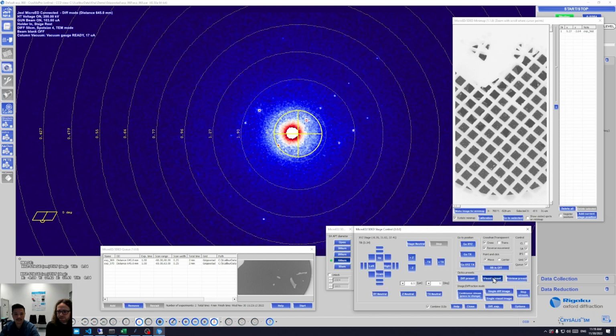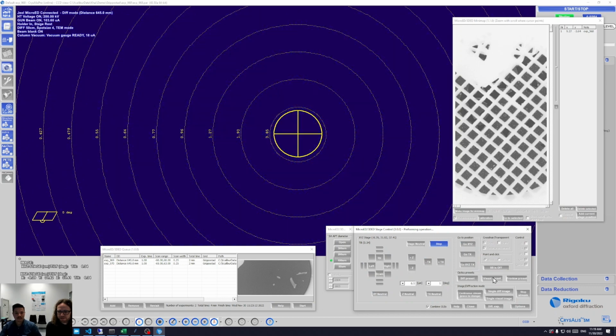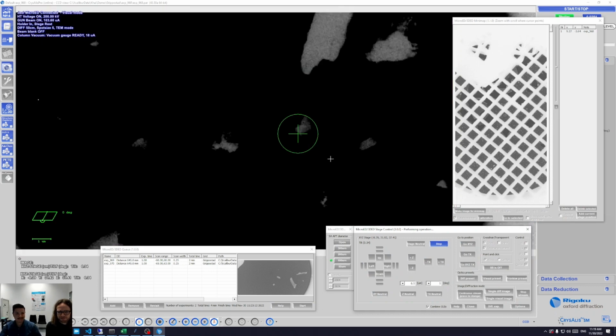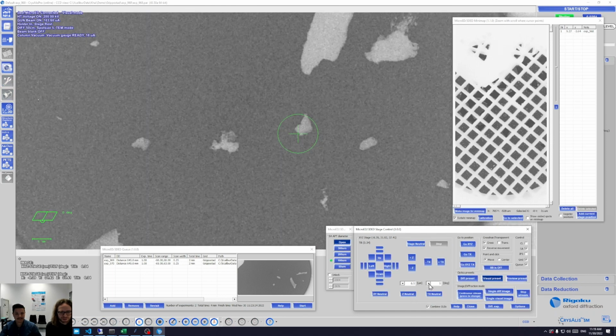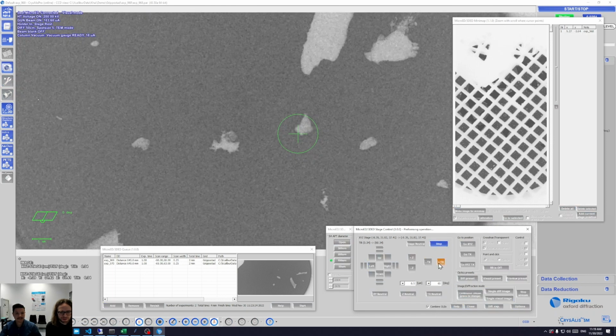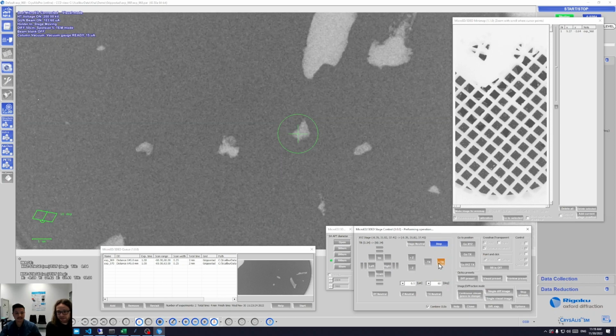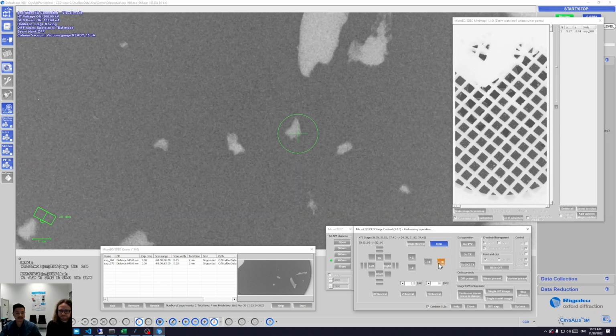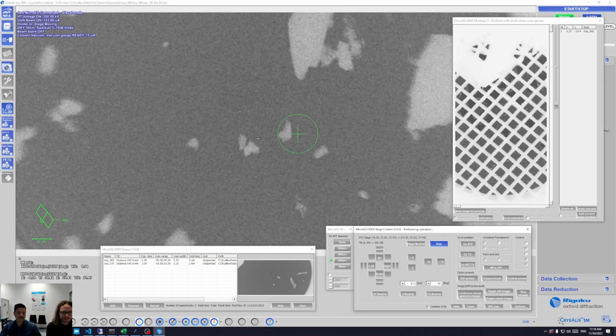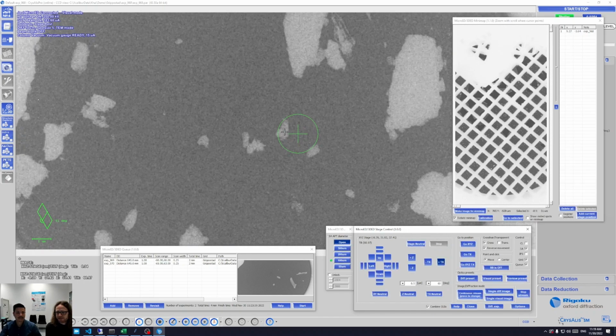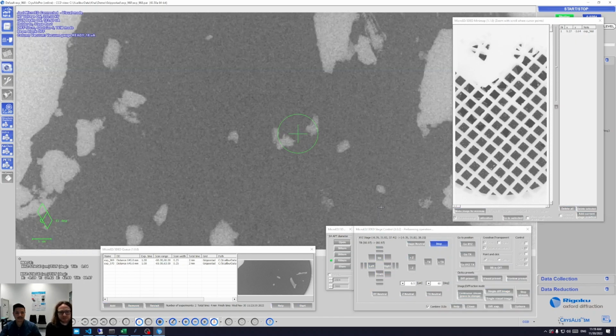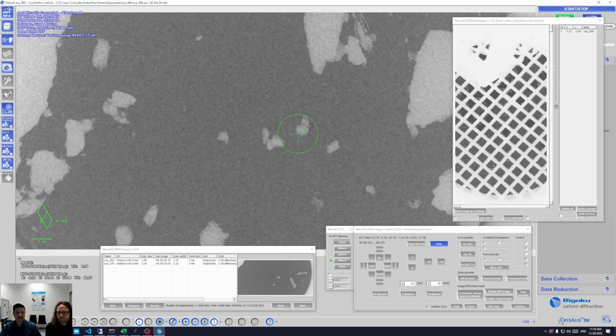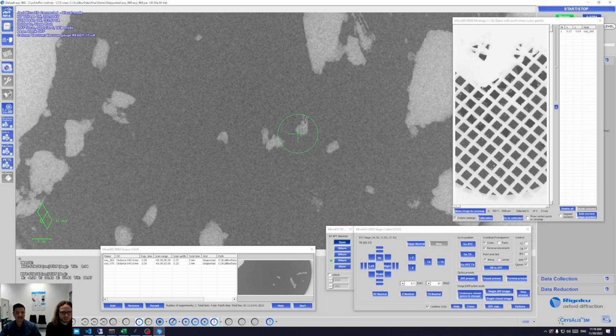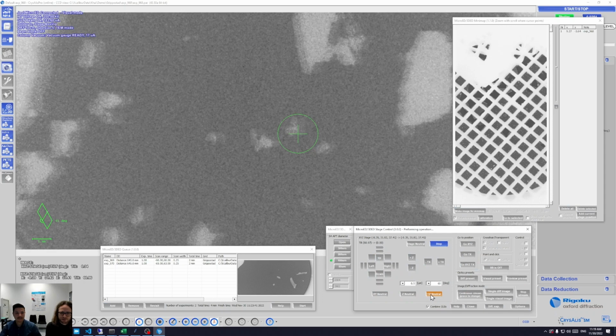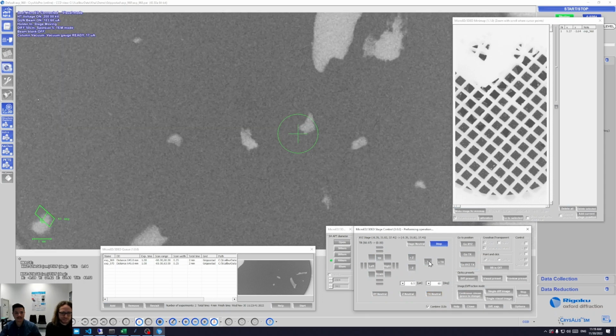And one more nicely diffracting grain just in the vicinity. Very nice. Often you have to search for a bit longer, but admittedly this is not a particularly complicated sample. It's one of our standard test samples, so we know it works nicely. If you have a true research sample, of course, often you spend some more time on finding grains that really diffract nicely.